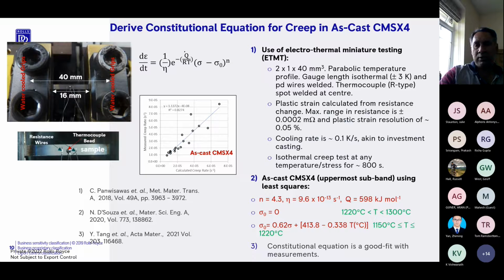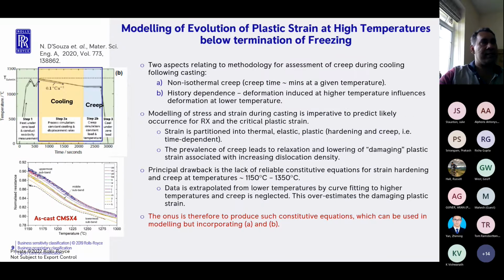So what we really do in these experiments is we take a specimen, we heat it to a certain temperature, we cool it down to a certain temperature, and at that temperature we do a very short-term creep test. At the end of the creep test, we cool the specimen down and effectively do a series of these tests at a given cooling rate, but for a series of different temperatures. This is an example of one such test. You can do the same test at a number of temperatures.